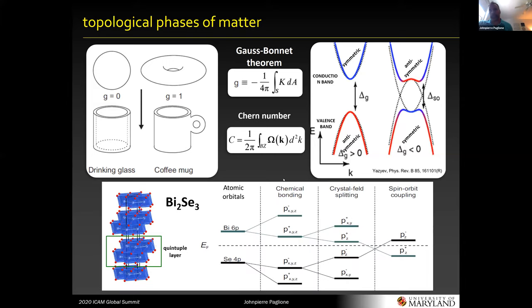The canonical topological insulator that arose in this fashion was bismuth selenide, which we worked on several years ago and continue to work on. The very general idea is that you put bismuth and selenium atoms together into a solid lattice, and the atomic orbitals go from being isolated to bonding. Some energy levels get pushed down and some get pushed up and they may cross. In particular, the p orbital bonding orbitals cross and give you this twist — this non-trivial topology. This adds a whole new dimension to research in condensed matter physics that wasn't captured in any textbook used over 10 years ago.